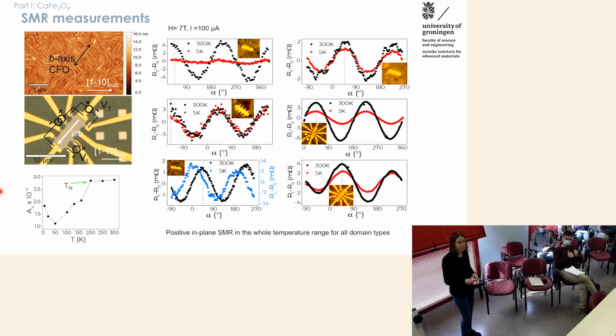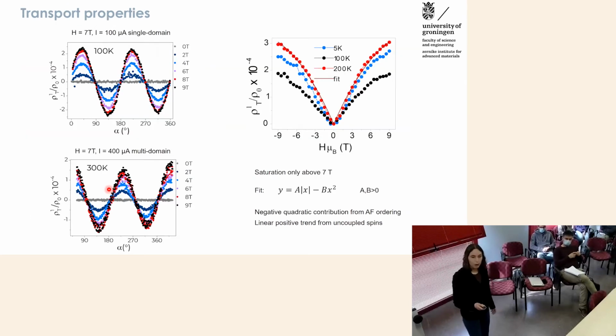So what we see is that we have this antiferromagnetic component, which is stronger at low temperature and then decreases as we approach the Néel temperature, but the positive component is always there across the whole temperature range. And if we look at the field dependence of these two components, none of them saturates with field as is typical for a ferromagnet. One of them, the positive one, scales linearly with the field, which is consistent with paramagnetic or at least non-interacting spins. And the antiferromagnetic component scales quadratically with the field. So this is telling us that we have indeed this antiferromagnetic component, and in addition, a component which looks like it comes from non-interacting or uncoupled spins.